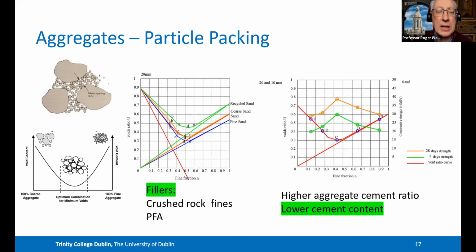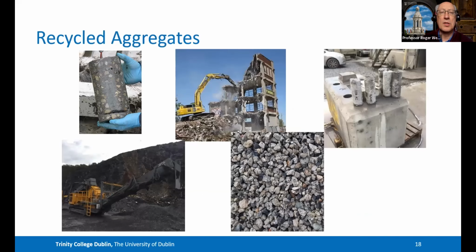We have some flexibility. So a lot of people have been using fillers for many years, but I think we should be using fillers for all our concretes, not just high performance concretes, not concretes which are for pre-stressing work, for example, 80, 90 megapascals. We should use fillers for many of our concretes in order to minimize, let it be driven by the cement.